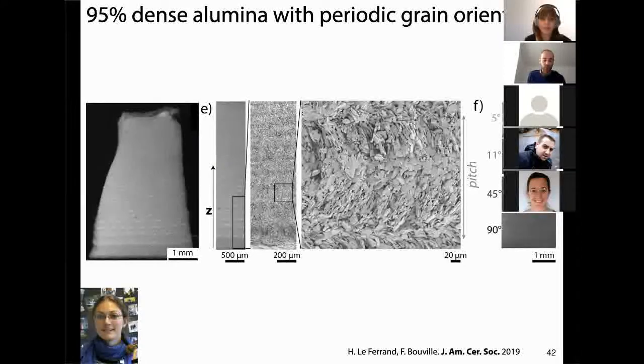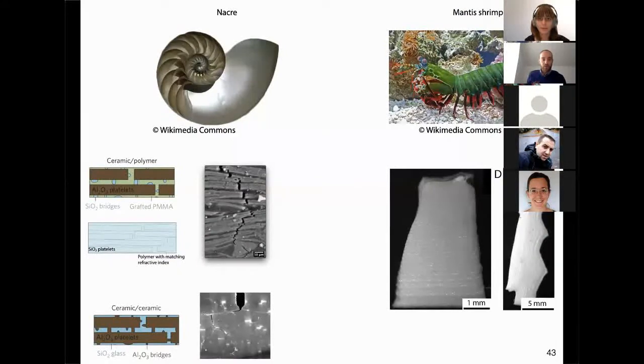And if you look at the microstructure when you zoom in, you can see that we have grains again that have these Bouligand structures. So grains like this, then grains like this. And we can change the pitch the way we want just by changing the way we cast our sample, so the time for the rotation of our magnet. So that being said, I think we're through with the 45 minutes.